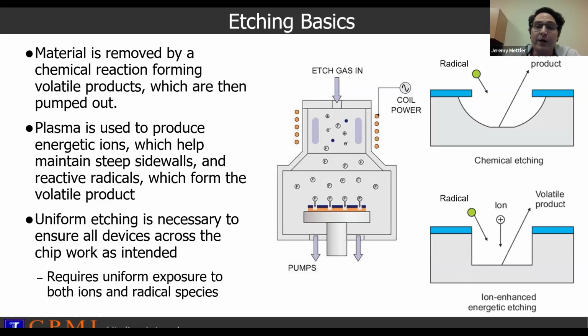And for that, you need both a uniform distribution of ions and radicals reaching your wafer surface. Ions are relatively easy to measure. They're charged particles. There are lots of different techniques for measuring the population of ions in a plasma. Radicals are highly reactive and very, very short-lived, and they're neutrally charged, and so they are a little bit trickier to measure. Historically, they've been measured primarily using spectroscopic methods. However, the downside to that is that it is not spatially resolved. And so you can get a volume average of the radicals in your process, but you can't resolve how many radicals are at a given spot.